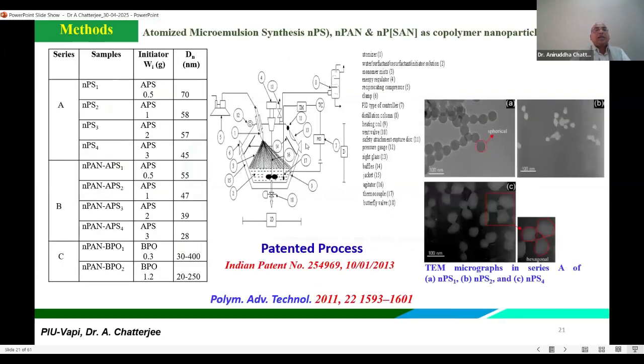So this is another process, the atomized microemulsion process. This is my patented polymerization process. Actually, I patented it in 2013. By that atomized microemulsion process, I have synthesized polystyrene nanoparticles, polymethyl methacrylate, polyacrylonitrile nanoparticles, and also the copolymer of polystyrene and polyacrylonitrile nanoparticles, that is polystyrene acrylonitrile as a copolymer nanoparticle. So here you can see that we have achieved a highly crystalline, hexagonal nanostructure of polystyrene